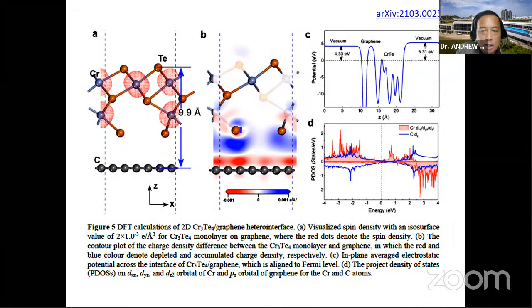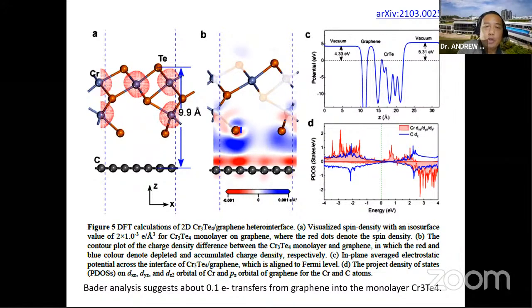This is some calculations that was done by a collaborator. And the blue and the red show charge transfer that occur at this interface. We grew it on graphene, right? We grew it on graphite, but the simulation was graphene, which approximates one layer of graphite. And our main conclusion was that by doing a Bader analysis, there's about a transfer of about 0.1 electron per atom from graphene to monolayer Cr3Te4, which we attribute to be some of the causes for this higher Curie temperature.